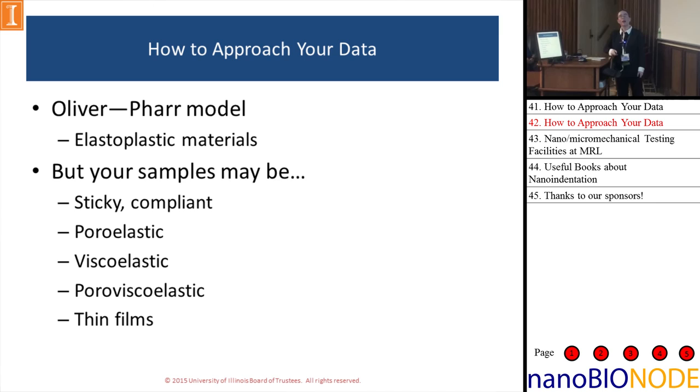You can have poroelastic samples, which are porous, and you may have fluid flow through them that you need to consider. Viscoelastic samples need time-dependent testing, because if you do your indents at 5 seconds to load into your sample, and somebody else does the indents at 2 seconds to load into the sample, you're going to get different results. And it's not because either of you have done bad indents, it's just because your sample has different properties at different loading rates. Poroviscoelasticity gets complicated.